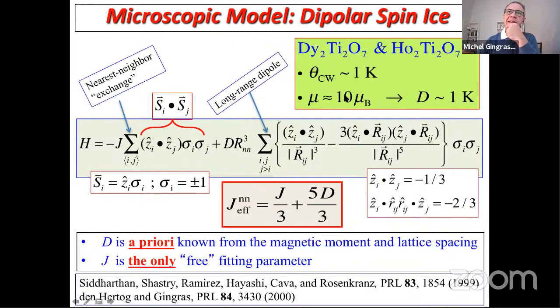So in holmium and dysprosium titanate, the Curie-Weiss temperature is about 1 Kelvin, but the magnetic moment at low temperature for dysprosium and holmium is huge. It's about 10 Bohr magnetons. And so if you estimate the dipolar energy scale between two nearest neighbors on the pyrochlore lattice, you get a dipolar energy scale which is also about 1 Kelvin. So these materials, their thermodynamic properties, are very much governed by the magnetic dipole-dipole interaction. It's not like transition metal ions where the dipoles are a very small perturbation to the Hamiltonian. It's the main part of the Hamiltonian.